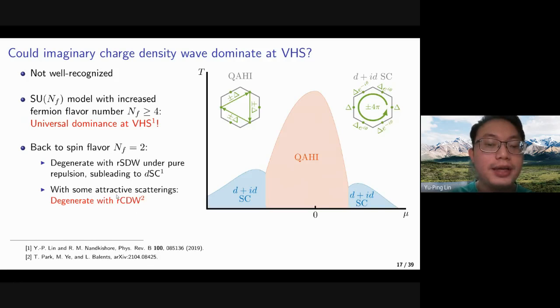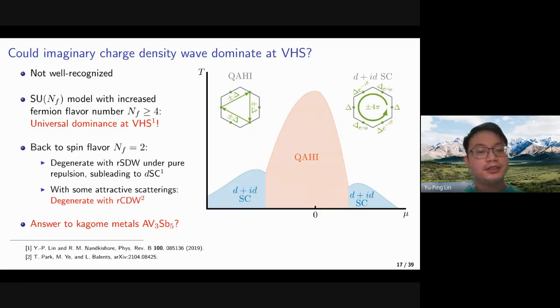So a recent work did a more complete RG analysis for the spin flavor equal to 2 case, where they introduced some attractive scatterings among the saddle points. And it turns out that with some attractive scattering, the imaginary CDW could be degenerate with the real CDW as the leading instability. So this poses the question of whether these imaginary charge density waves could be the answer to the unconventional CDWs in the kagome metals.